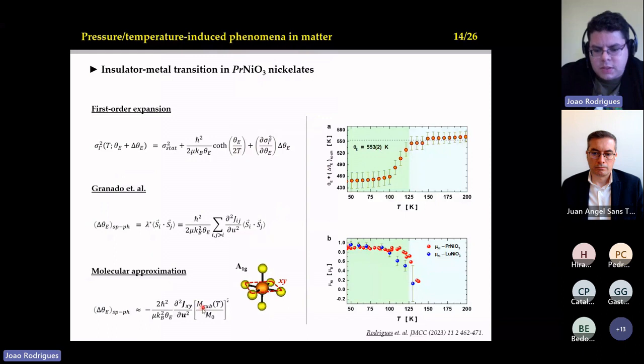And then you use a molecular field approximation to determine, and then to prove, how this phonon coupling is changing the Einstein temperature at the onset of the magnetic transition, okay? And then this kind of curve for the Einstein temperature with temperature is very related to the magnetization of the sublattice. So we could combine, for example, the neutron data that we have here in red, and then you can use this neutron data to describe this curve here using this molecular approximation. And then we discovered, using this EXAFS data, that this spin-phonon coupling is mainly occurring because we have an interaction between the phonons from the most symmetric mode in the plane of the octahedra and the spins, okay.